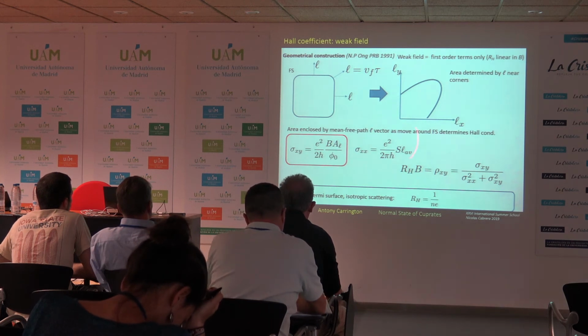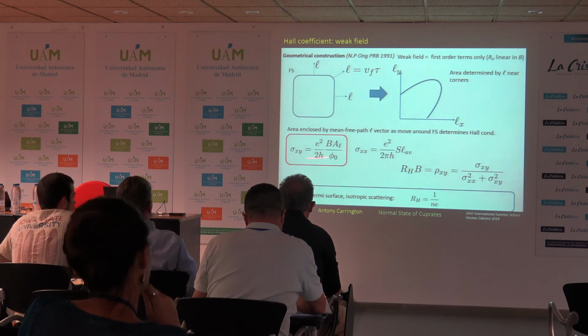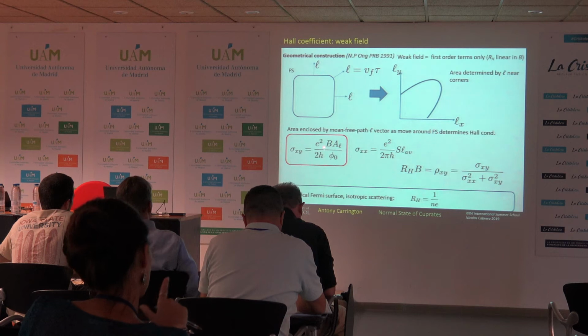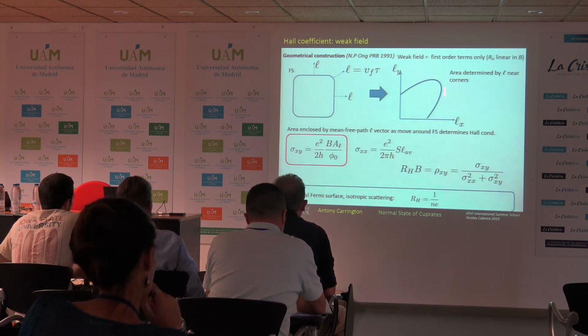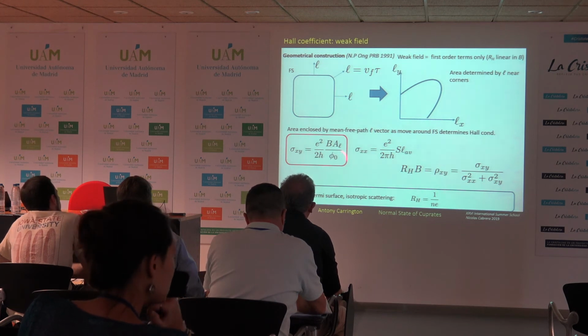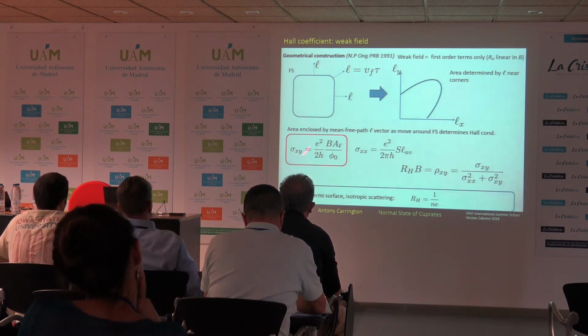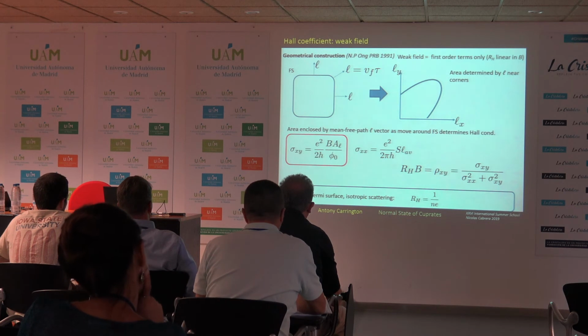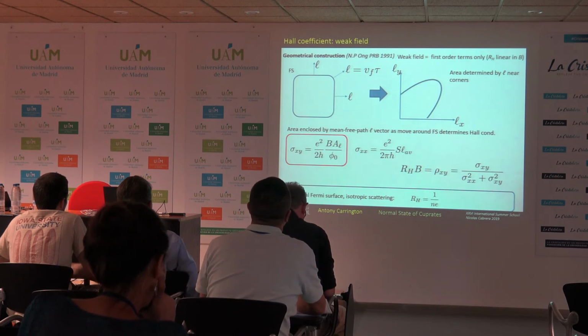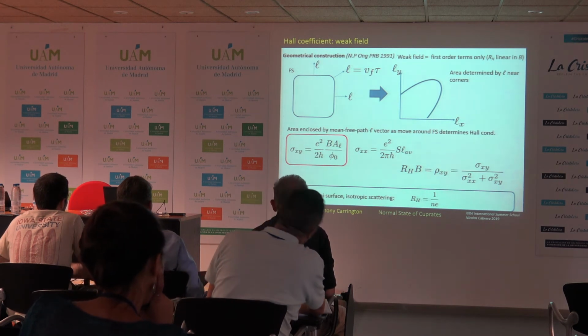Then Ong showed that the Hall conductivity, sigma xy, is simply the magnetic field times the area traced out by this l loop divided by the flux quantum times the quantum of conductance. So it's a very simple geometrical way of looking at the Hall conductivity.